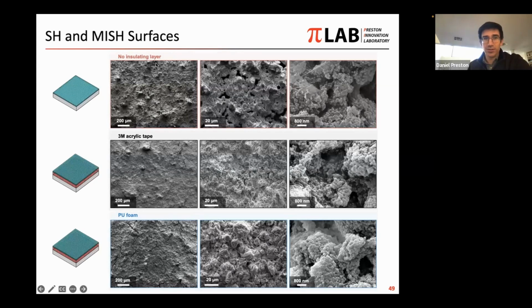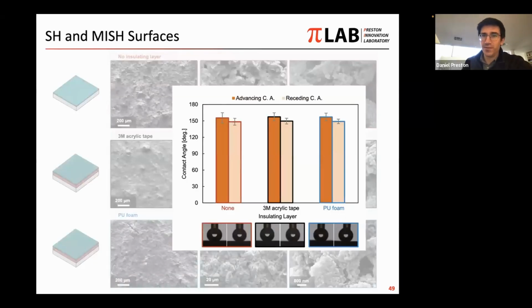And so we look at the textures of the just super hydrophobic coating compared to the texture of the one with the foam beneath. Texture looks almost the same in these two cases, as well as another case where we used some acrylic tape as the insulating layer. Chemistry also is the same because we have the super hydrophobic spray-on coating as the topmost layer. And we did probe the advancing and receding contact angles and found that in all three of these cases, they were essentially the same values. So we keep the texture and the chemistry the same, and we change only the thermal performance using this insulating coating.